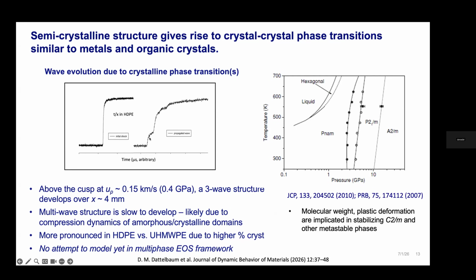Those transitions, those waves, are related to crystalline phase transitions. So they overlap fairly well with what's been measured in diamond anvil cells. There's a group in Italy that did a lot of work on polyethylene. It's associated with these transitions between the monoclinic and orthorhombic structures. And that's associated with that cusp at about 0.15 kilometers a second or 0.4 GPa, and that multi-wave structure is more pronounced in HDPE versus the ultra-high molecular weight because it has a higher percent crystallinity.